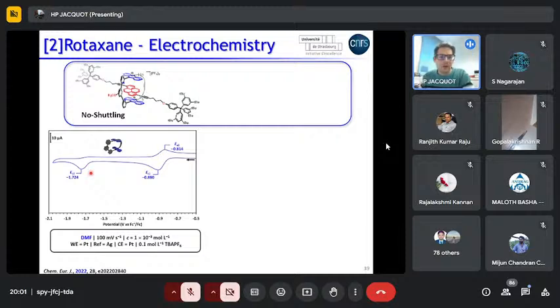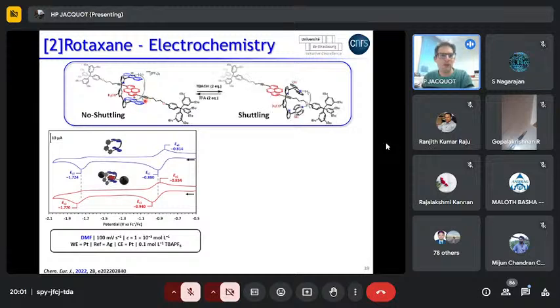So what about the rotaxane? It has exactly the same behavior, an EEC mechanism, but both reduction waves are shifted towards the more negative values. So this is expected for the first redox process because the recognition site gives some fixed electronic density to the acrylamide cores. But even after reduction, the macrocycle still feels the presence of pyrene since it's harder to reduce. So you have no real shuttling even after reduction.